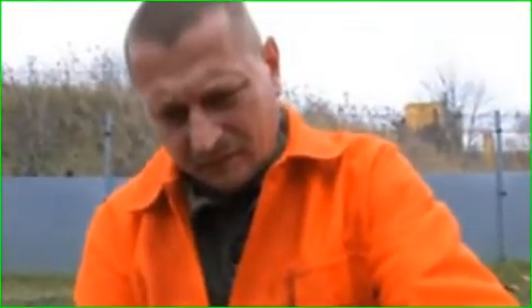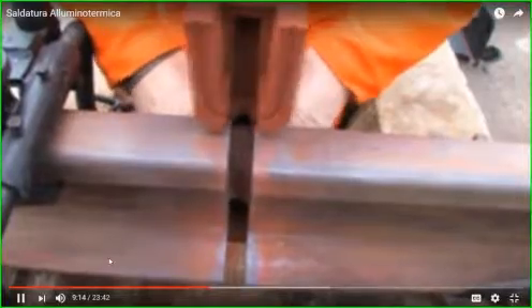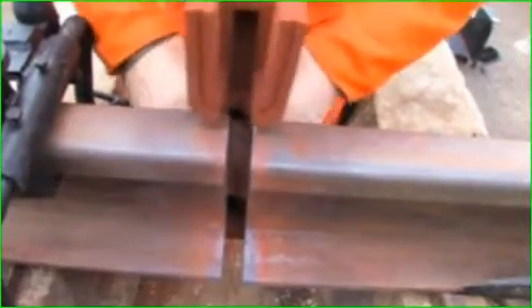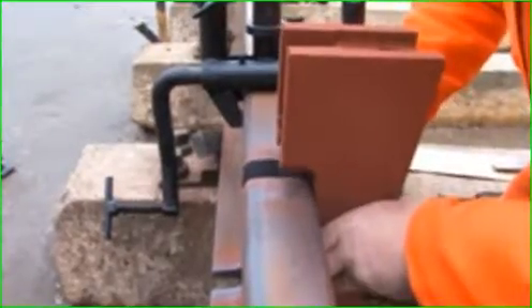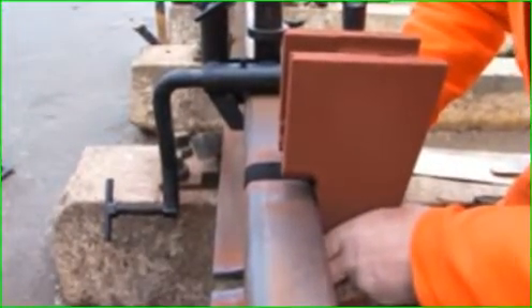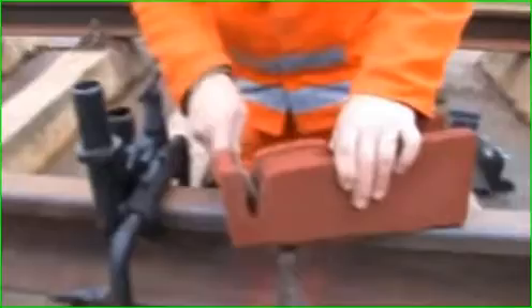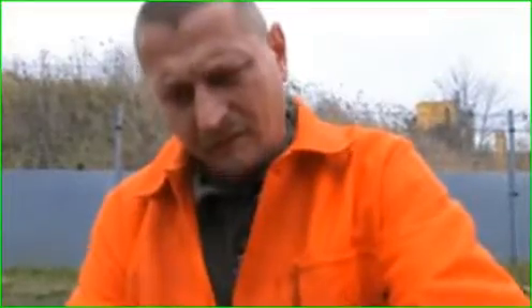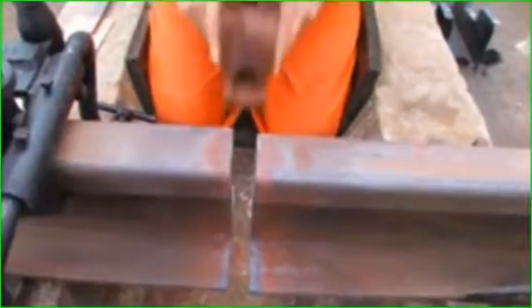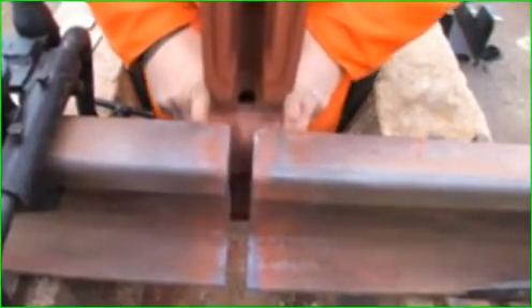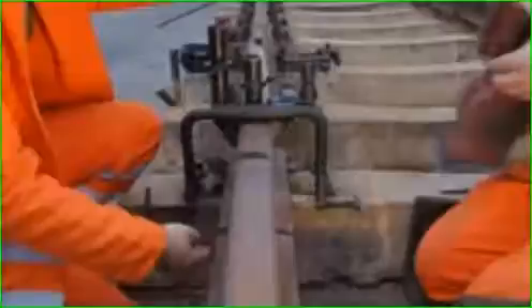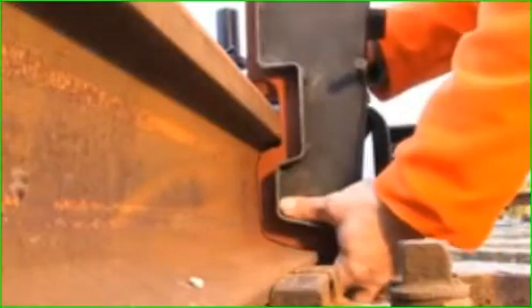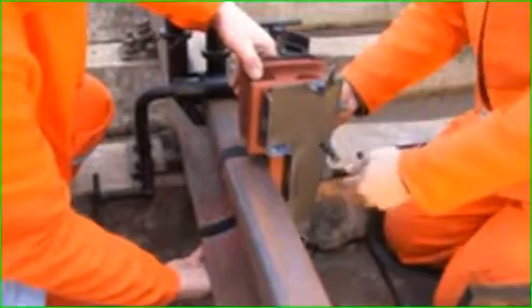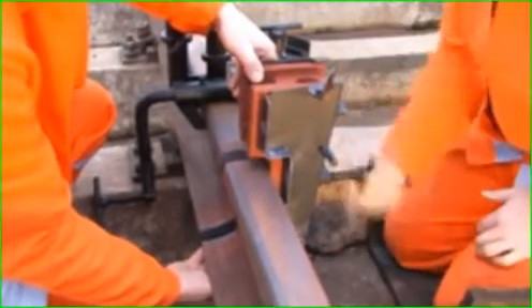Due to the different milling tolerances of the rails, it may become necessary to renew the correct fitting of mould to rail, done by careful rasping. If a rework of moulds by filing is required, the collar geometry must always be kept. If it's impossible to comply with this, then use special transition moulds. The moulds are to be inserted into the mould shoes and then set to the rails one by one, but not at the same time.